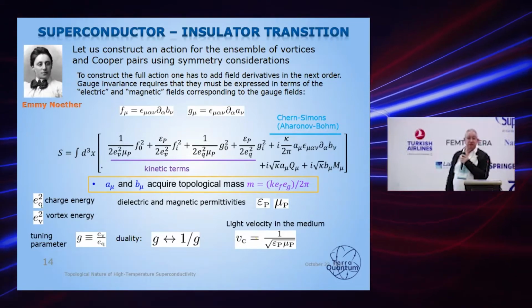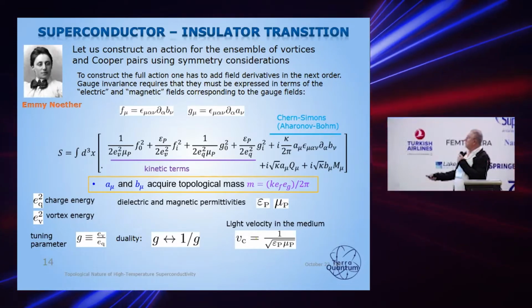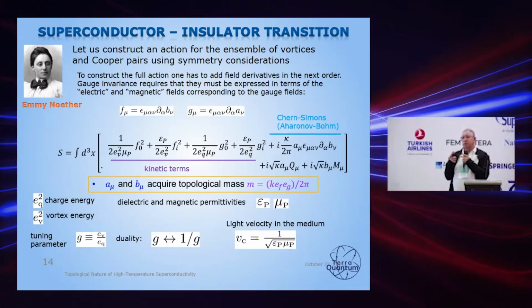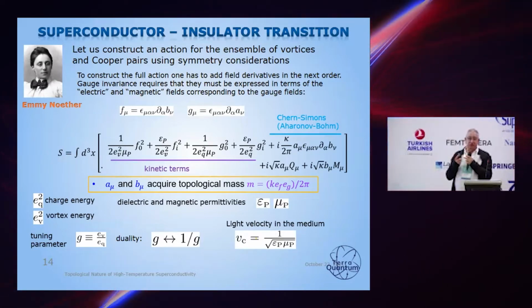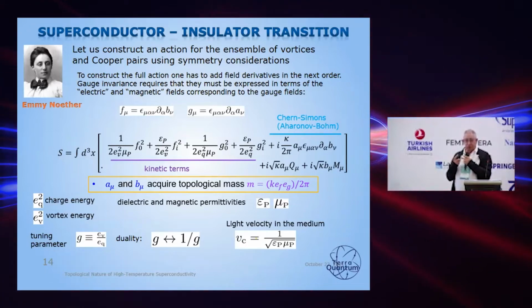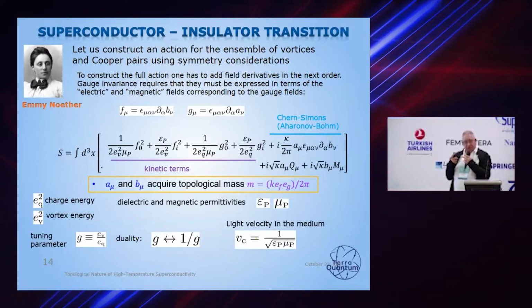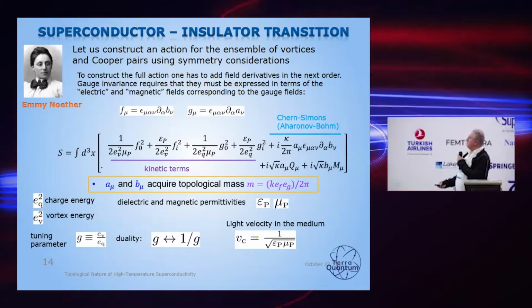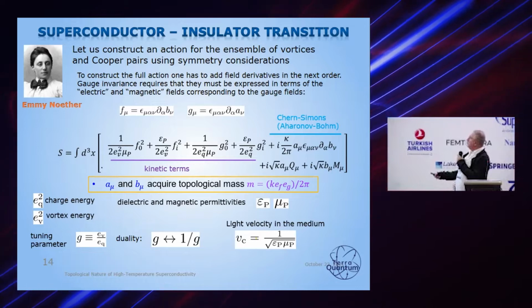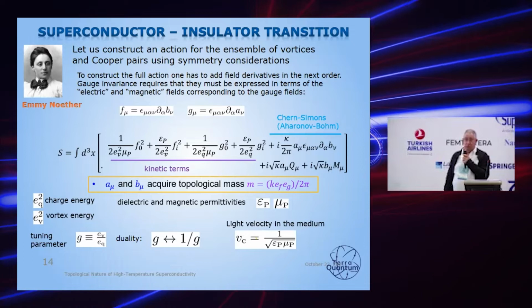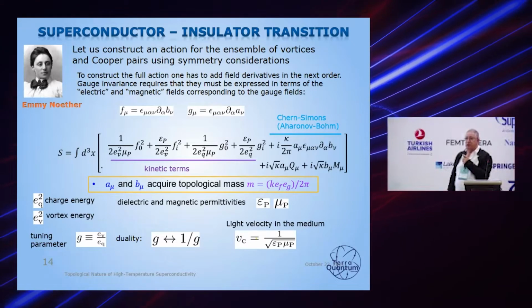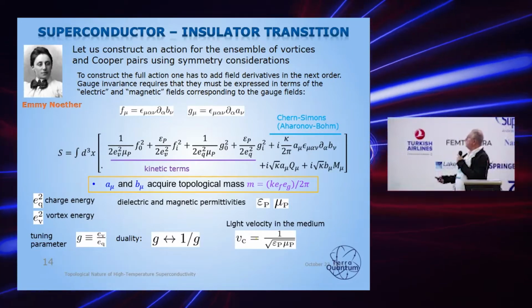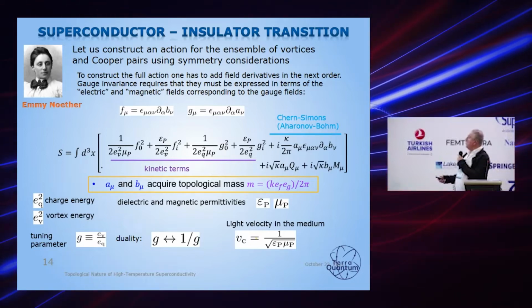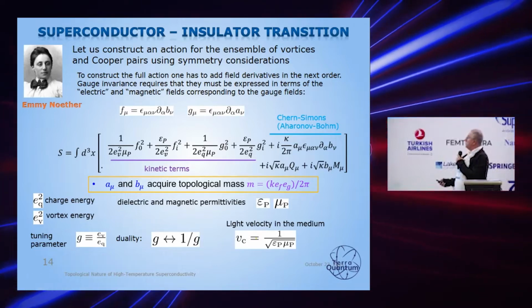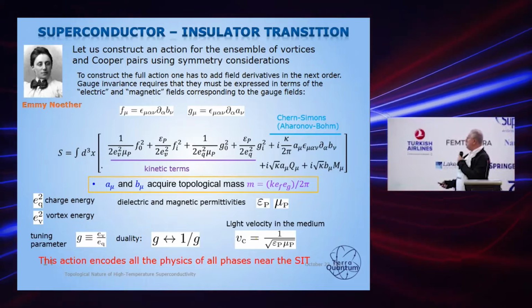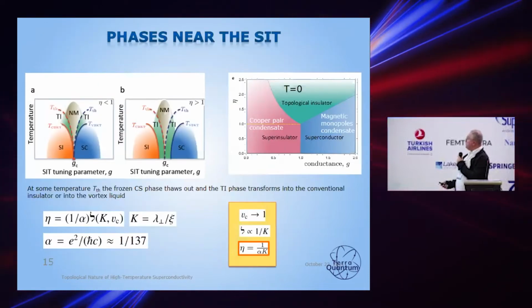Then, people working, for example, on charge density waves know very well that together with the term describing the elastic properties of the charge density wave and the potential energy related to the phase of the charge density wave, we have to have a crossing term responsible for the topological mass. And we exactly have this Chern-Simons term here, quantifying the Aharonov-Bohm interaction, whose importance for the superconductor insulator transition was overlooked. So this is a completely dual action. Basically it encodes all the physics of the superconductor insulator transition and describes all the phases which appear near the point of the superconductor insulator transition. And this is the summary.